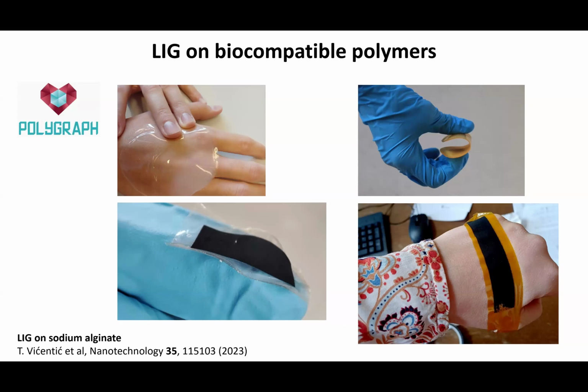Often in the case of Kapton, graphene doesn't stick very well to it. It depends on the quality of the Kapton that you buy. So sometimes it just kind of falls off with use, which is not what you want. The first thing we did, even before starting Project POLYGRAPH, was LIG on sodium alginate. This is a material that is extracted from algae, and it's so biocompatible that it's often used as a food additive, so it's edible actually. And we found the correct laser parameters to make LIG on it, and we published that in this paper you can see here.